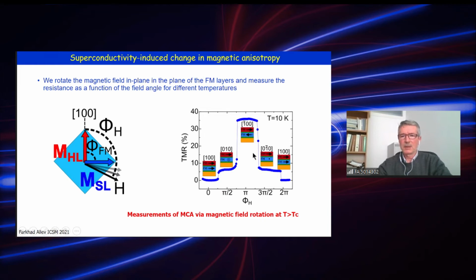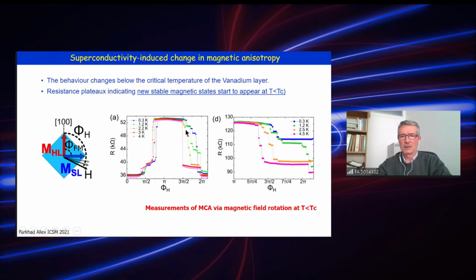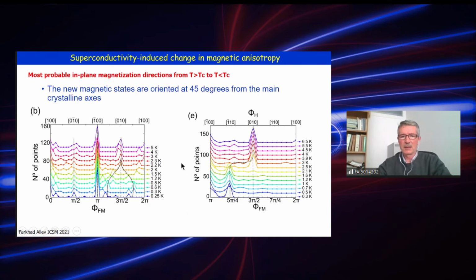But in the superconducting state, when we rotate the magnetization, we observe the appearance of new states which correspond to the hard layer, hard direction. We analyze this by making histograms depending on whether we start rotation in the anti-parallel state or from the parallel state.